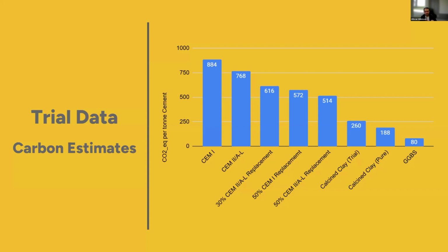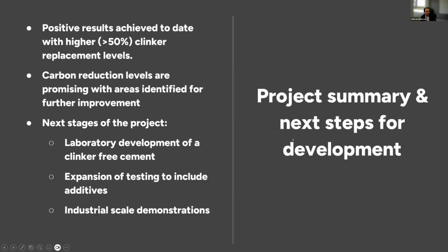So for us, it's something that's very interesting moving forward, being able to combine that carbon reduction while still retaining good performance. You'll notice that there's a difference between the trial and the pure calcined clay. The trial material has a little bit of contamination with limestone, so we've met with an issue with calcium carbonate decomposition, but again, something we're working on.